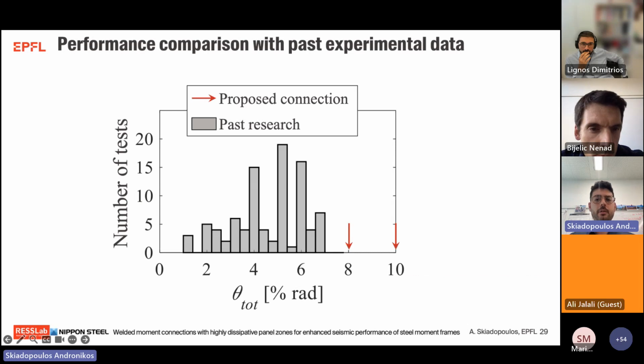The remarkable performance of the proposed connection is also highlighted in this histogram, where we compare the performance of past research in terms of achieved lateral drift demands. And what we see is that available connections in literature withstand 2 to 7% story drift ratio, contrary to the proposed connections that exceed 8% story drift ratio without any strength degradation.